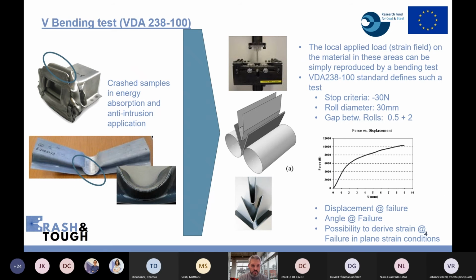On the left side of the slide, we can see some crushed samples. Here we have only lab samples, but they are very representative of what happens, for example, in an axial crush of a front rail or rear rail, or even a crush box. And here we have a bending test performed on a sample, which is representative of a bumper beam or, for example, a B-pillar. And we can see that in the highly strained areas, the metal is actually folded.